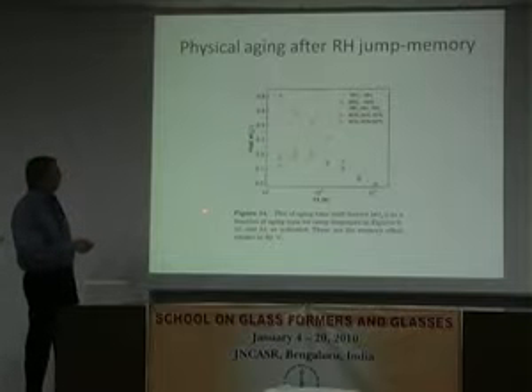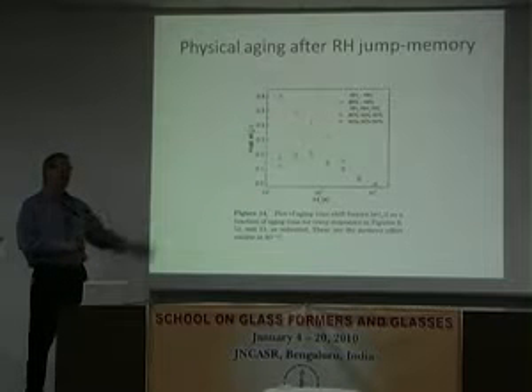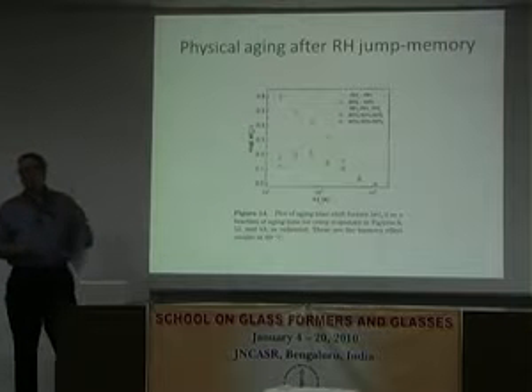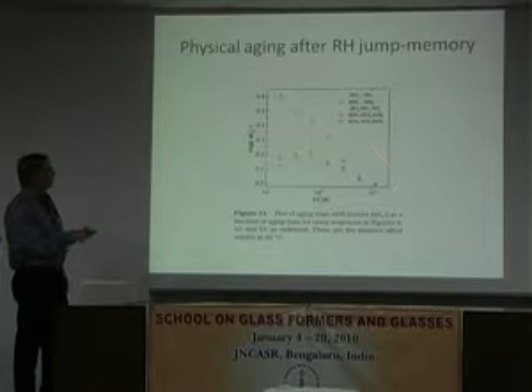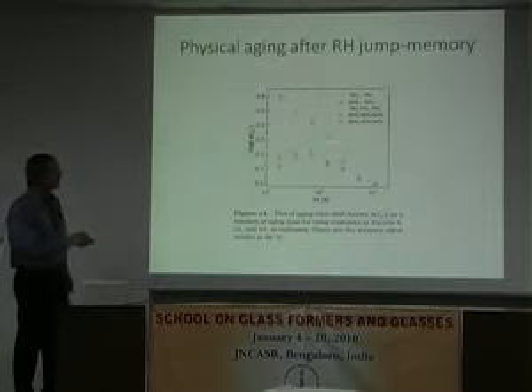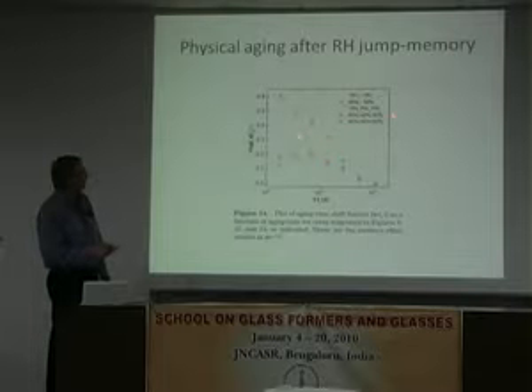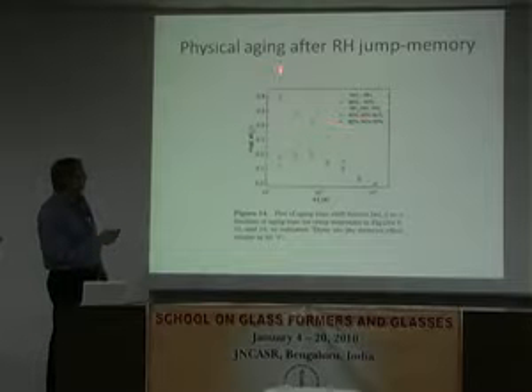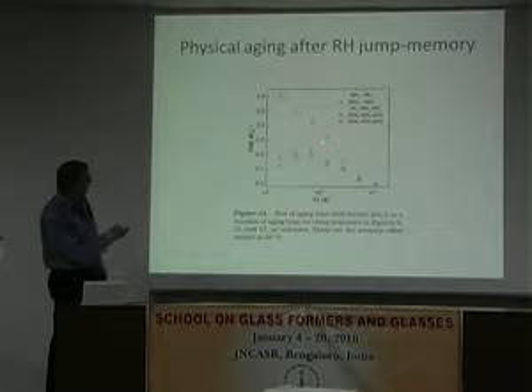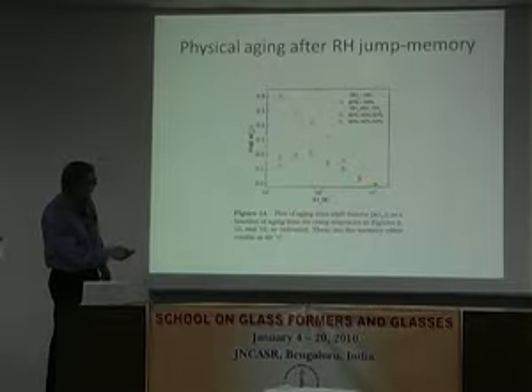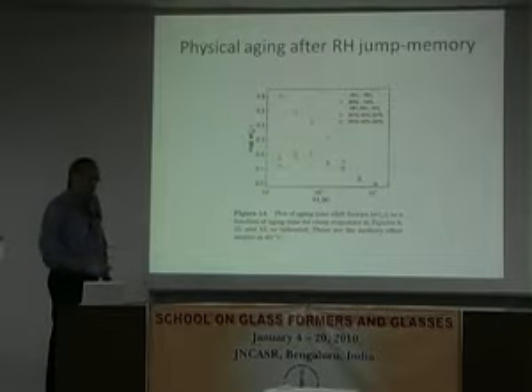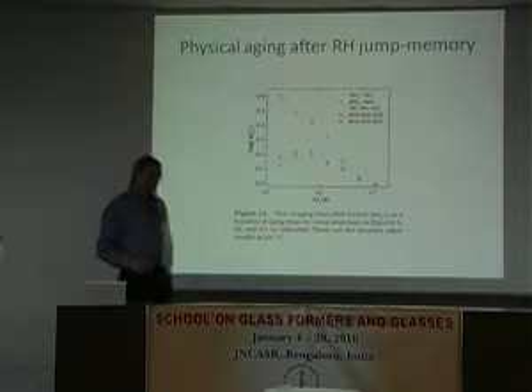So this would show that if you just blindly applied elapsed time and expected a power law for this history, you wouldn't get it, right? So that's just the point of that. And these are these two-step histories. And this is the one step downwards where you do, of course, get something close to a power law until it starts relaxing towards equilibrium. So just to slow you down. No, that's fine. That's fine.